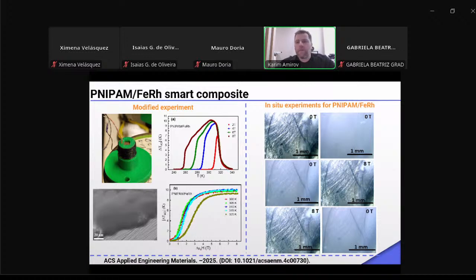And the same experiment in here, we have the converse, the inverse effect, because we deal with inverse magnetocaloric effect. Apply magnetic field, it's cooling down. So first we apply magnetic field, and as you can see, the polymer is cooling down and going to swollen state. And when you remove magnetic field, it's going to dehydrated state.